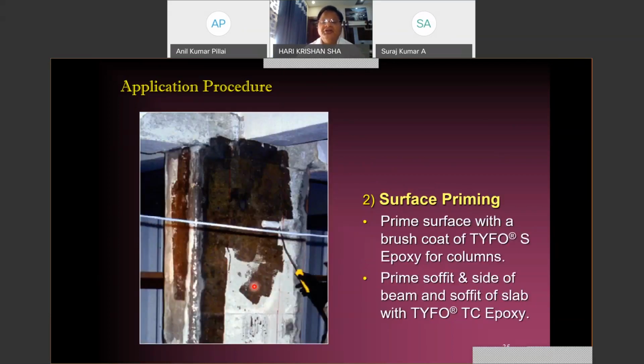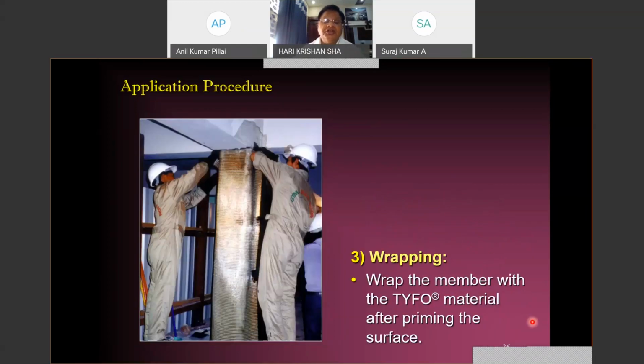Once the surface is prepared, it is painted with a surface priming coat. Prime the surface with a brush coat of epoxy, and prime the soffits and sides of the beam and slab also with an appropriate epoxy. Once the surface is primed, this fiber sheet is wrapped all around. So wrap the member with the fiber material after priming the surface, and it is just like a bandage.